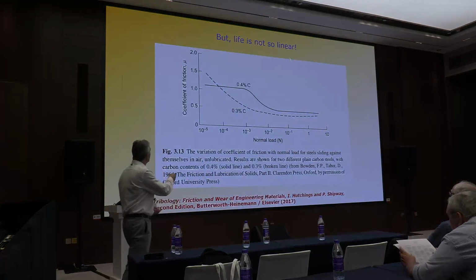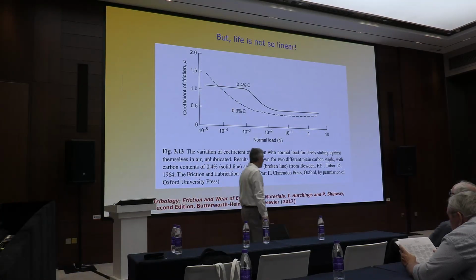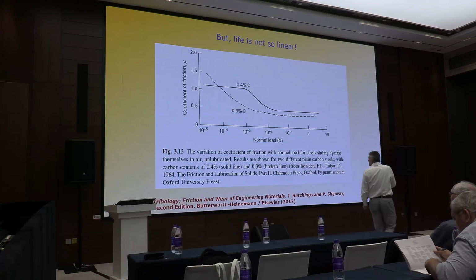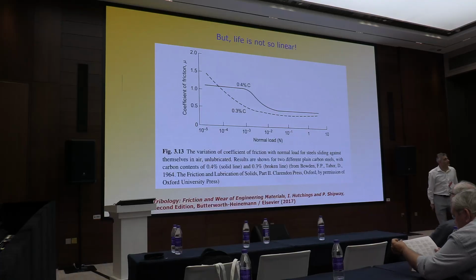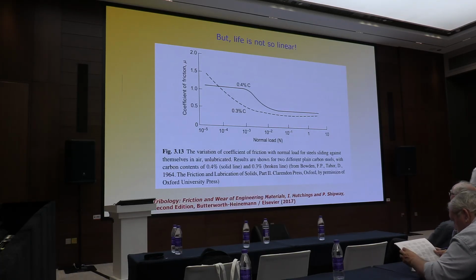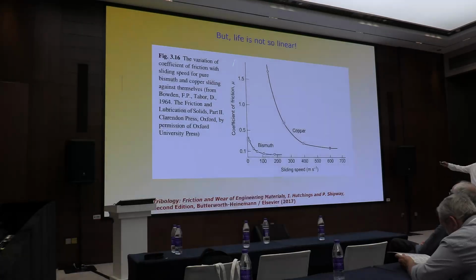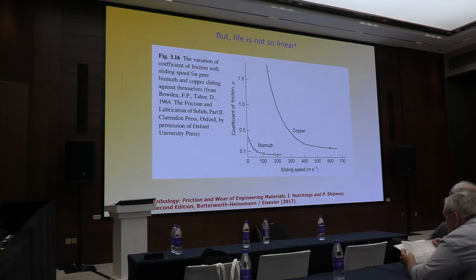But what will happen? Life is not so linear, you know, we know that. Here you can see that the coefficient of friction depends on the normal load. It's not linear or constant. It has a dependence, unfortunately, or fortunately, it depends on the point of view. Also, life continues, not so linear. Here the coefficient of friction also depends on the sliding speed. You have the dependence: the friction changes with the sliding speed of the tip, or when we have two surfaces, it depends on this velocity.